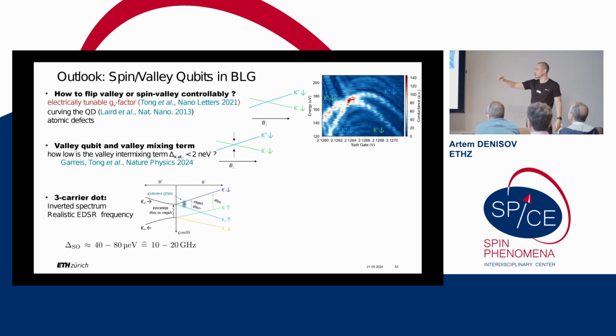Another interesting direction is to look not at the single carrier dot, but at the few carrier dot. Because a few carrier dot is like a single carrier dot, but the spectrum is inverted, because it's like you remove one carrier from a full shell. And a full shell in graphene has 4 carriers in it, right? The interesting thing is that your ground state and your next excited state are not moving away from each other as a function of magnetic field, but rather move closer to each other.